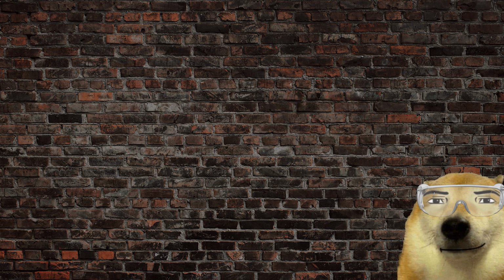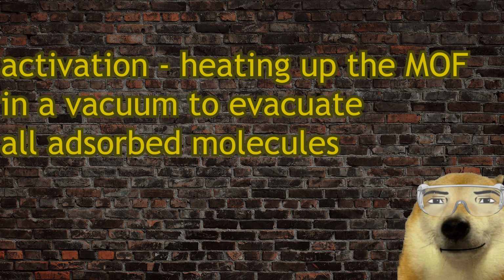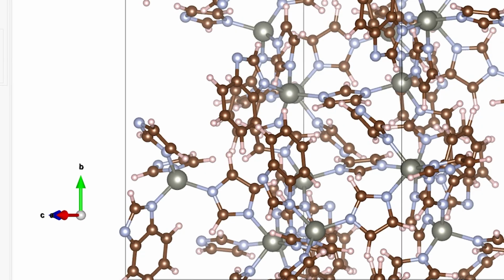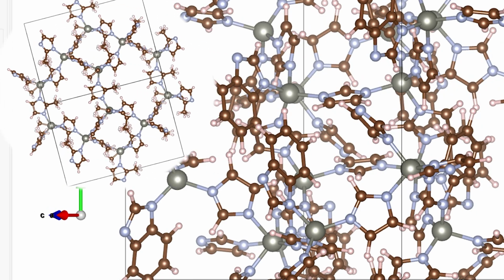That may sound large, but because the material is reusable after activation, it can cycle repeatedly and capture much more over time. Compared to other well-known MOFs like ZIF-8, ZIF-62 performs significantly better at low pressures. At around 1 bar, ZIF-62 absorbs roughly 4 times more CO2. At higher pressures, ZIF-8 catches up, but for real-world, low-pressure capture scenarios, ZIF-62 has a clear advantage.